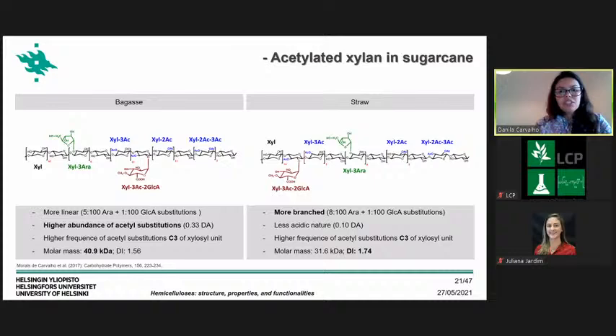And the acetylation distribution were quite similar between the different parts, the different materials. Of course, they were quite similar in terms of the distribution, but not in terms of the amount. And the molar mass of the xylan in bagasse was quite high compared to that from the straw, although the xylan from the straw was more diverse, which means that there was more variability in the molar size for straw than that from the bagasse.